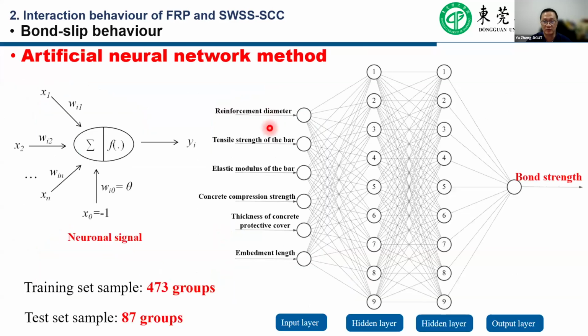And therefore, we try to extend further research, using the artificial neural network method to predict the bond strength with the following input factors, including the bar diameter, the tensile strength of the bar, the elastic modulus of the bar, the concrete compression strength, the thickness of the concrete cover, and the embedment length. In total, 560 experimental data were collected to establish the database.